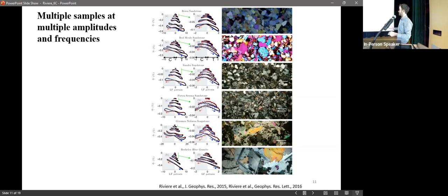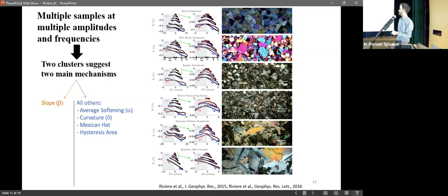So this was work done in Los Alamos, actually. We basically do some DAT measurements for a variety of rock samples at multiple amplitudes and frequencies. And what we see is that when we try to find some correlation between the nonlinear parameters, we have two clusters. So this suggests that there are maybe two main mechanisms behind the response that we measure. The slope of the signature is not correlated to any other parameters. All the other parameters are correlated with each other, except for the slope.